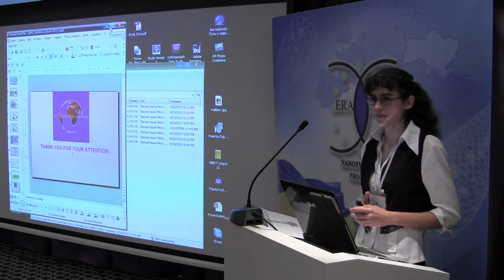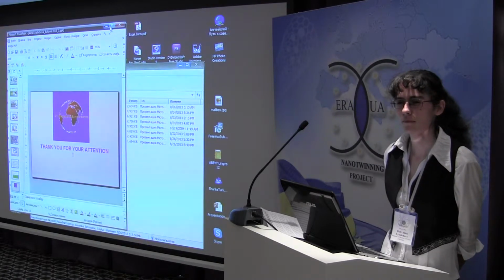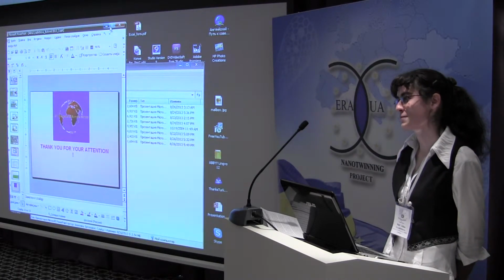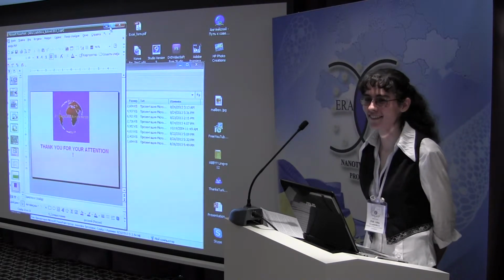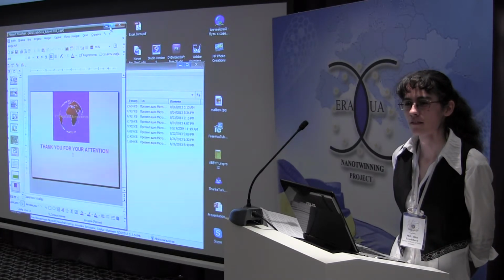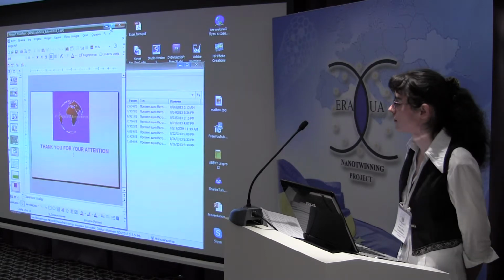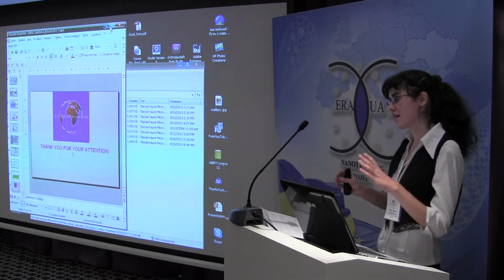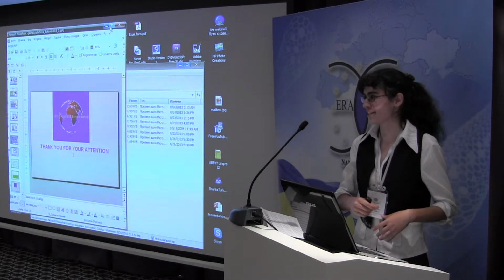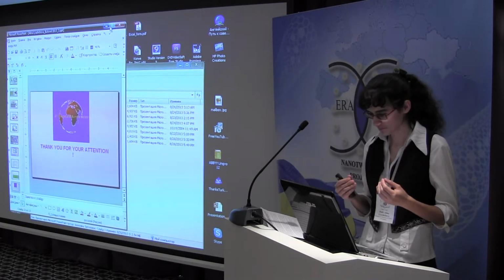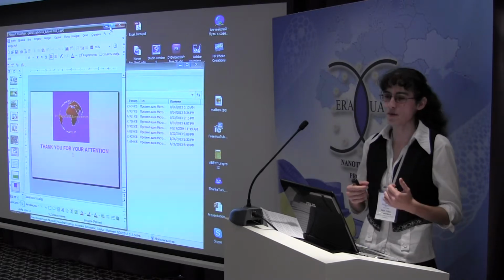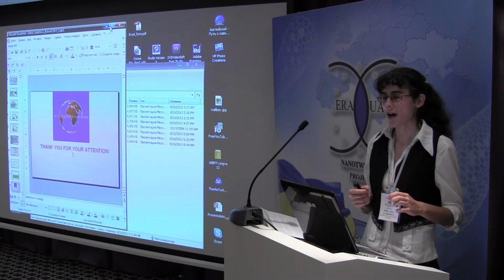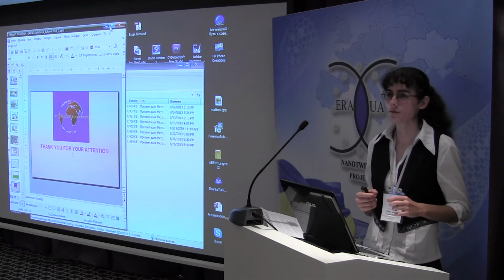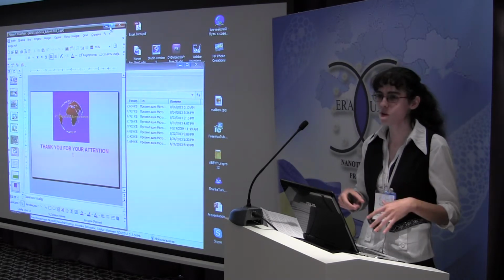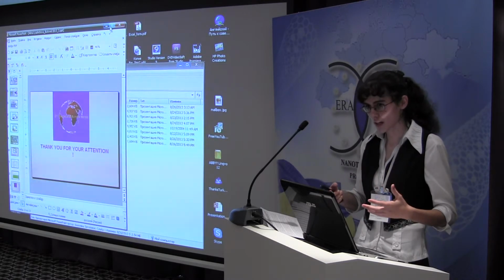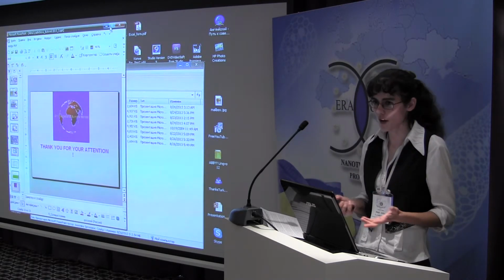Another question: did you measure the size with a different technique, I mean AFM, SEM, or whatever? How did you measure the size of the particles? The lateral sizes were obtained from the TEM images. The thickness of these nanoplatelets was determined from the absorption spectra as one of the linear sizes of a quantum box, because we observe a quantum confinement effect.